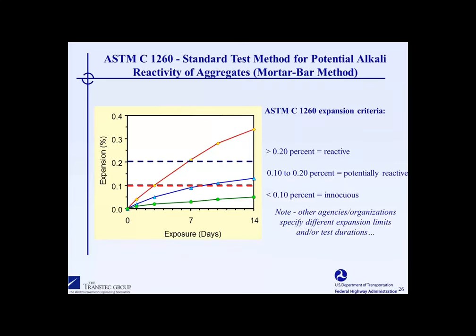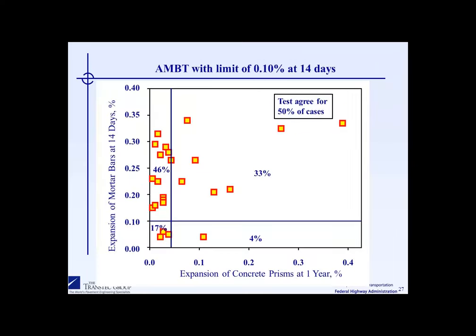In terms of expansion limits, the most common limit used is a 14-day criterion with an expansion limit of 0.1%. ASTM C1260 also has some other classifications: if you're between 0.1 and 0.2% expansion, you'd be considered potentially reactive, and anything above 0.20, you would be considered reactive. We'll revisit this later when we talk about the AASHTO protocol, but what we've recommended in our federal highway guidelines and in the AASHTO recommended practice is a 14-day test duration and generally a 0.1% expansion limit.